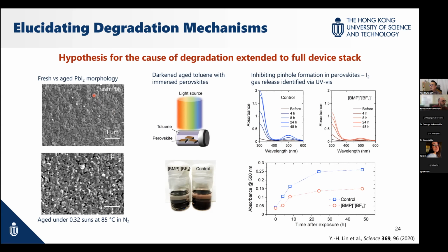So when we combine light and heat, even there will be a tendency to form the iodide, but under that kind of circumstance, it's difficult to maintain the iodide. So the iodide will continuously break down in this kind of harsh aging condition, combined light and heat, especially above 60 degrees Celsius. So these are the main findings from this work.